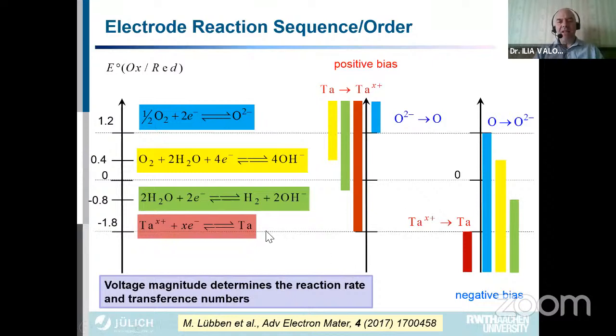And negative potentials have elements that oxidize very easily, such as, for example, tantalum or lithium. They have a very negative potential. On the other hand, you have the so-called noble materials, which have a positive potential, and they are not oxidized easily. For example, gold is a noble metal, but also oxygen. So this means for the devices that we can determine which reaction may take place or may not take place.